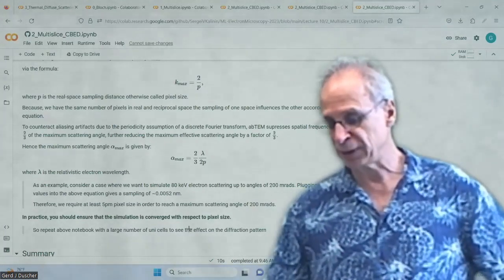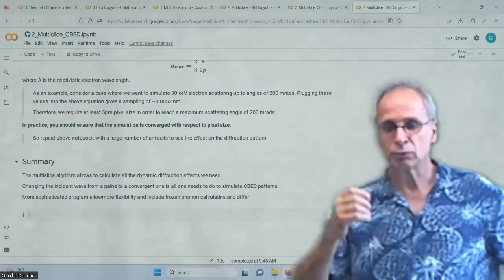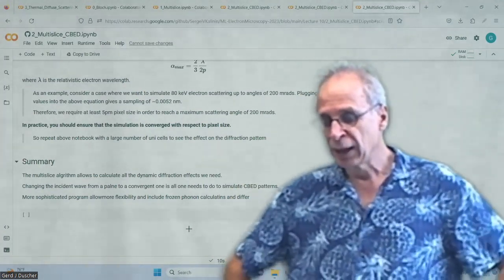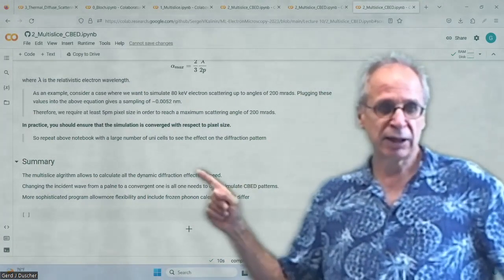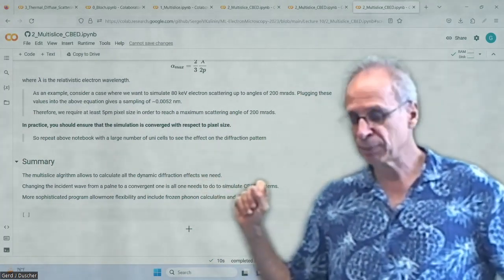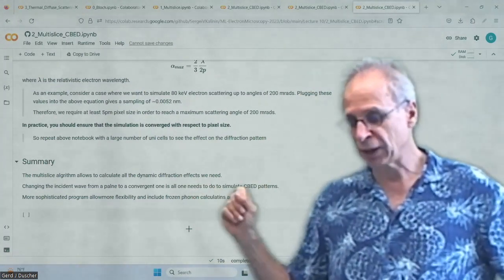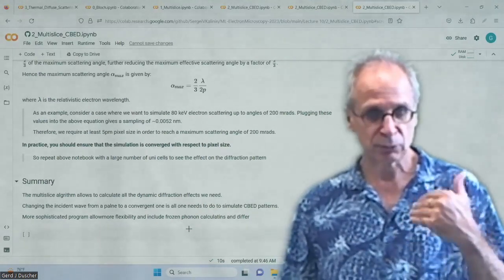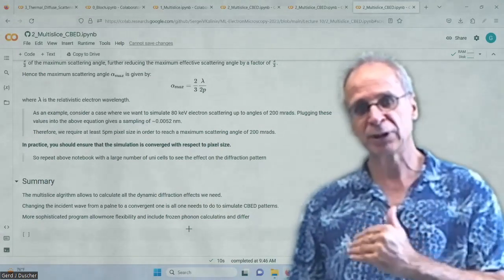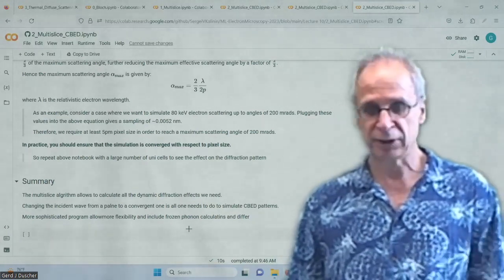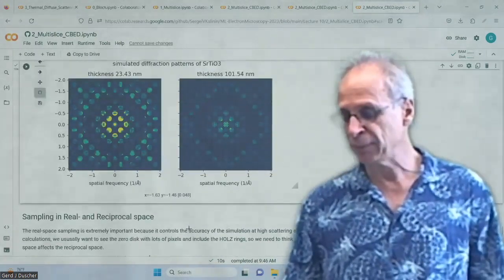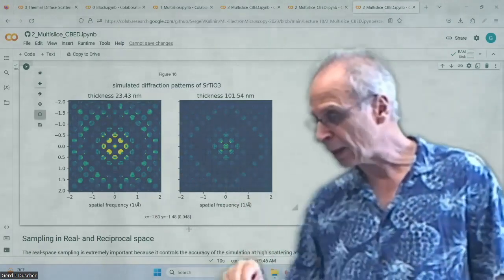We can get all the dynamic diffraction that we are having, and we get very reasonable results. You can do that a bit faster with more sophisticated methods, but this one is really directly from the textbook into matrix algorithms. You see it's already working quite well. But this is not a convergent beam electron diffraction pattern yet. What is missing is the thermal diffuse part of that. We are having a very, very large contribution from phonon scattering. Even going to zero Kelvin wouldn't help because you have your zero-point motion — the atoms cannot stand still — and I'm already starting to show that here.